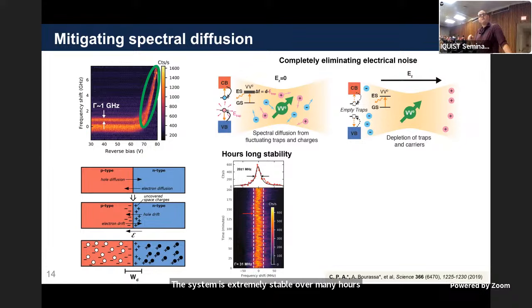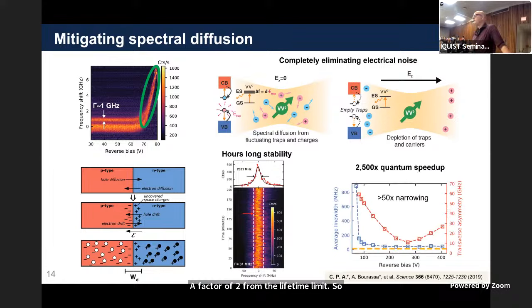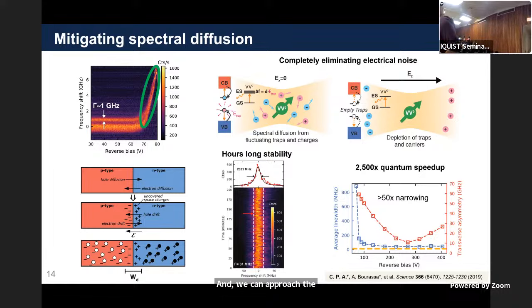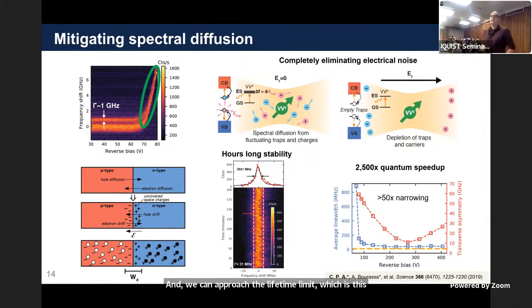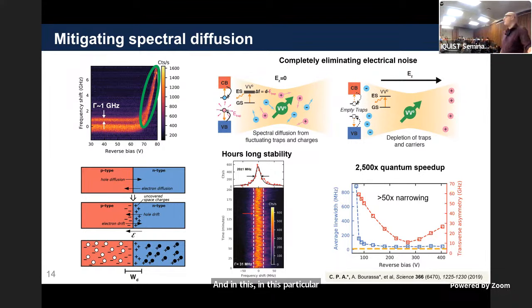So this is a measurement over 3 hours, and we basically only see a factor of two from the lifetime limit. So we have an extremely narrow line that's rock steady. And we can approach the lifetime limit, which is this dotted yellow line here. And in this particular sample, we saw a factor of 50 in the narrowing of this optical emission. So we have 40,000 line widths of tunability, and we also have near lifetime limited emission that we can engineer by playing with the semiconductor physics of the system.